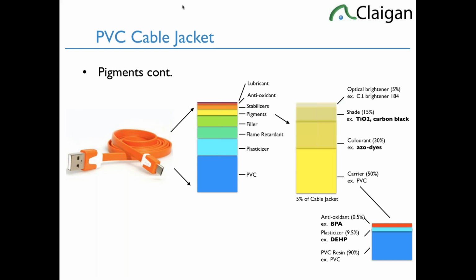So when we measure for, say, orthophthalates like DEHP or DINP or whichever in a PVC tube, when it's 100,000 ppm, it's because it's the main plasticizer. When it's 2,000 or 3,000 ppm, which is a non-compliance for RoHS or EU MDR, it's from the colorant. It comes in through the colorant. And this is very common. We see this in maybe 1 in 10, or 10%, of all flexible PVC. We see these low levels, 2,000 ppm, of orthophthalates.